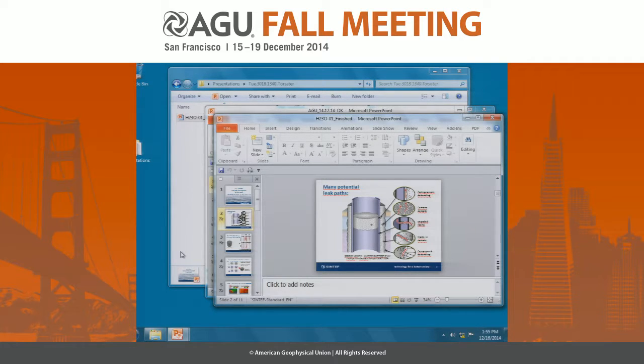but there's one study that I'm aware of, at least from the SACROC field, where they have actually taken some cores out from a well that has been used for CO2 injection. And what they found there is that the interface that seems to have had most CO2 leakage is the one between the cement and the rock, which is in agreement with what we see here, that we have more trouble with getting good bonding, especially due to the geometry. If you have shrinkage, cement might shrink inwards, and the cement-rock interface is maybe the one that is most critical.